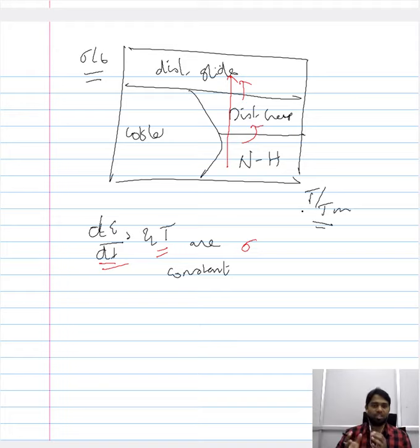Since for each creep mechanism we have a dedicated equation that relates the stress to the temperature, we can thereby calculate the corresponding rate at which the material would deform under this combination of stress and temperature. This is one of the useful ways of representing the creep behavior of a material under different stress and temperature conditions.